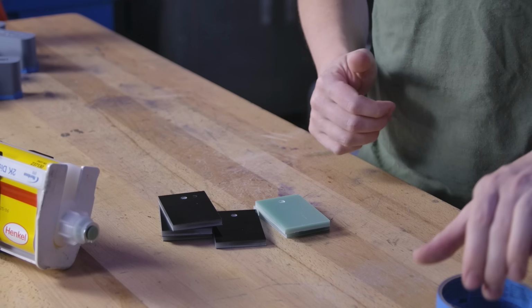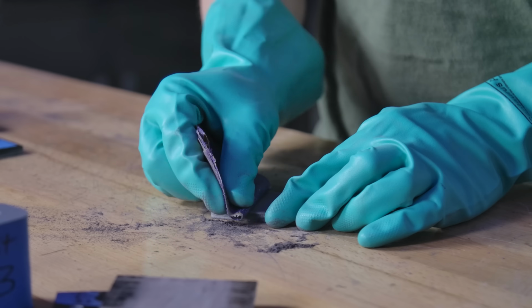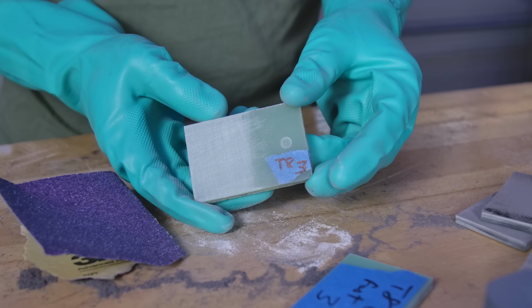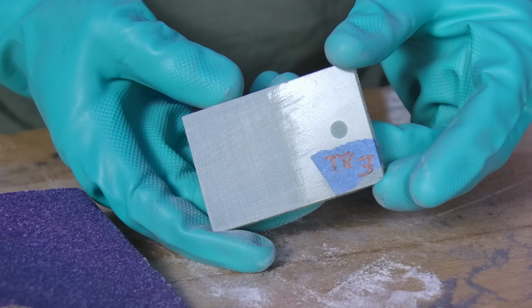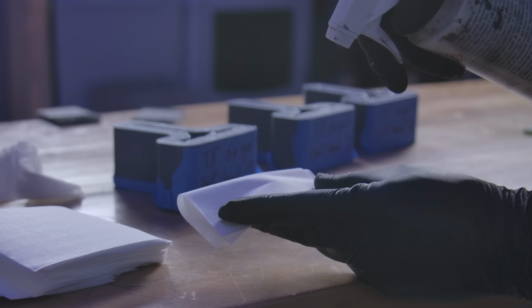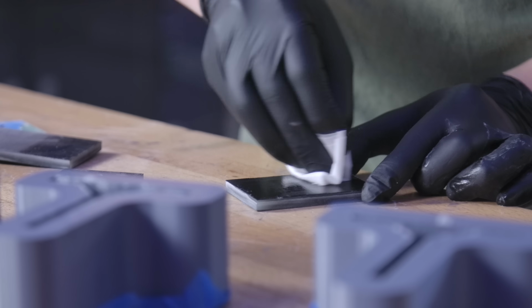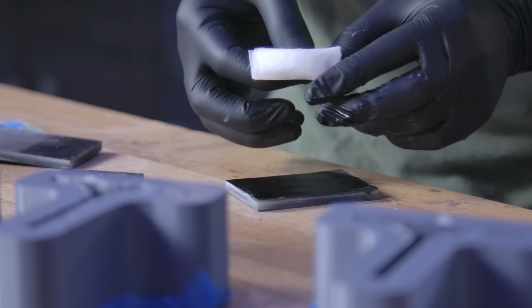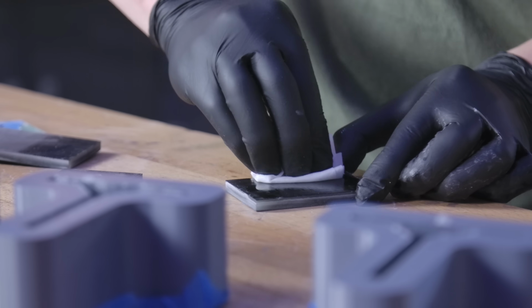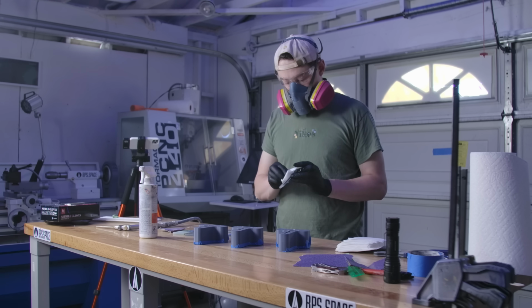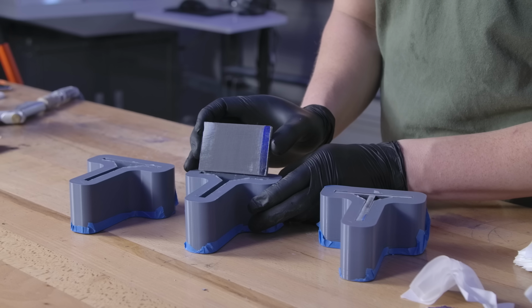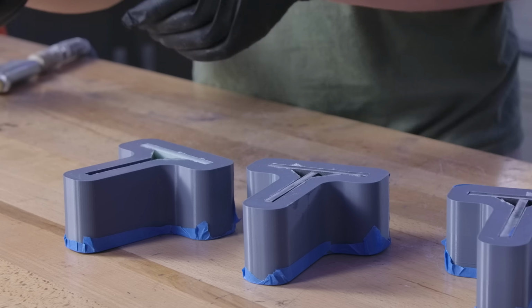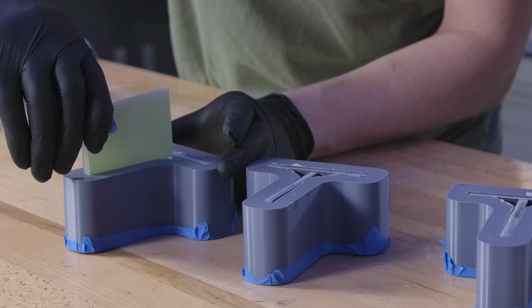I'm gonna prep 3 more samples, and they're each gonna use 60 grit linear sanding until the surface is completely gray. Then I'm gonna thoroughly wipe it down with high-grade IPA on a lint-free wipe, switching the sides of the wipe periodically to not reintroduce old contaminants. I'm starting to run out of fiberglass, so 2 of these are black fiberglass and 1 is green. As previously mentioned, while this is an uncontrolled variable, I haven't been able to find any correlation between the strength and the color of the fiberglass.